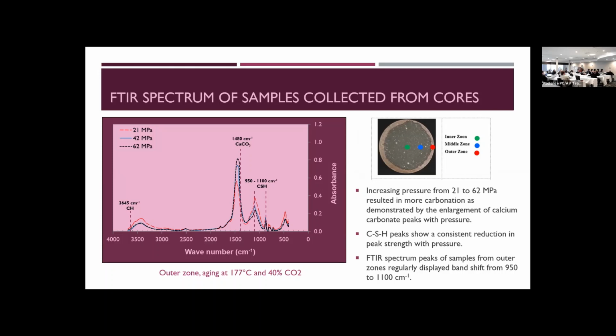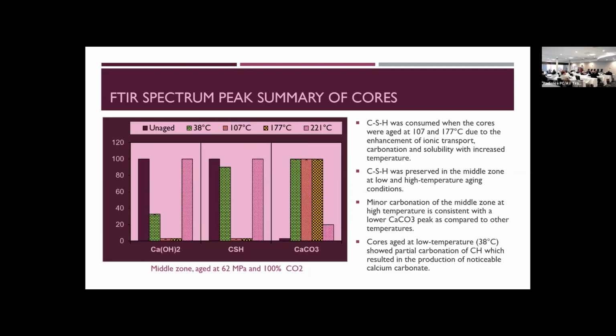Now we look at the spectrum peaks for the samples to identify whether we can locate some of the elements in the system. As you can notice here, we use samples that have been exposed at 21, 42, and 62 megapascal. We observe that the peaks are pretty much identical, with, however, a reduction of some of the elements at 21 megapascal. You can see relatively lower components in here, and the maximum was observed at 62 megapascal, which is something that was actually expected for our testing.